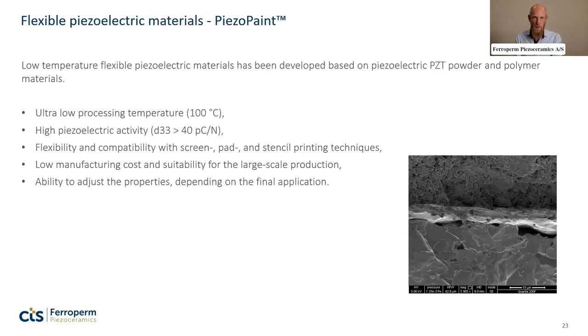So this is the proposed technology. We call it PiezoPaint, and I'll just spend a few moments on the micrograph that you have on the right. So in the center there, across from left to right, you have an electrode deposited on a substrate, which is kind of the bottom part of the picture, and then the top part of the picture is PiezoPaint. And it's maybe difficult to see here, but all it is really is piezoceramic particles suspended in a polymer matrix. So it's a composite, and of course the piezoceramic particles enable the piezoelectricity, and the polymer enables the flexibility and the possibility to cure at low temperatures.